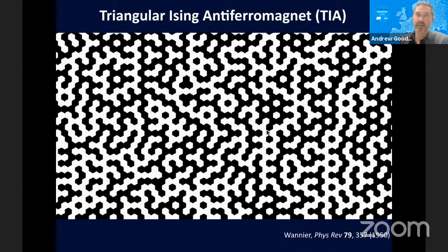There are. I'd say, just off the top of my head, the world where that's been done most is certainly in the case of frustrated magnetism, where the application of magnetic fields as a perturbation to watch what happens to a frustrated magnetic state in response to that field has been studied by many groups. I would say that this is one of the really nice aspects of these correlated disordered states, is that because you have this configurational degeneracy, they very often end up being highly perturbable. They're very, very susceptible to external fields. And I think it's absolutely no accident that good magnetocalorics or good barocalorics, for example, are often built on these same principles of geometric frustration and correlated disorder.